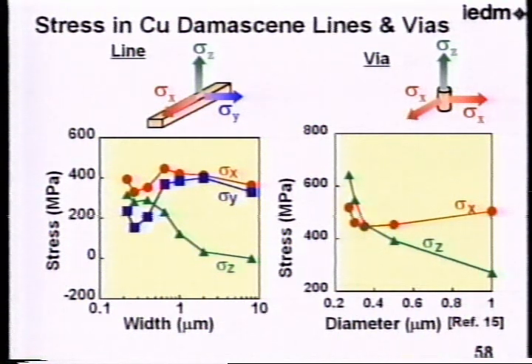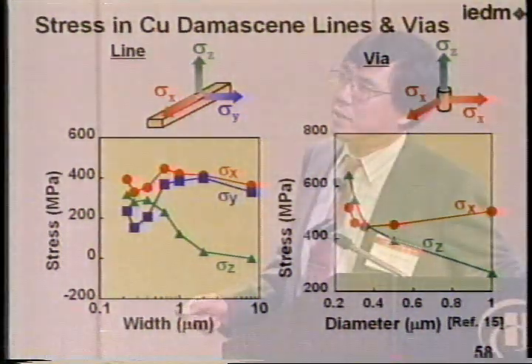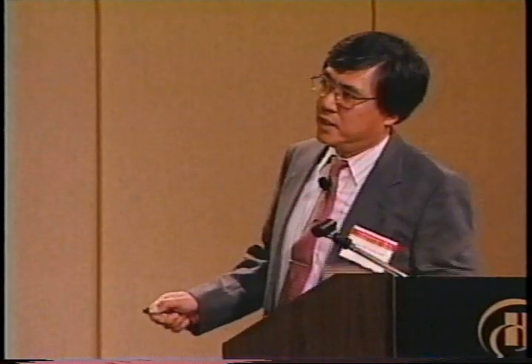To explain this kind of voiding failure, they measure the stress of copper lines and vias by using the X-ray diffraction. This is some result of stress and width, and also the stress as a function of diameter. The stress is divided in a Z component and X and Y component. And as you can see in this figure, there is very unique dependence of stress as a function of width and also as a diameter.